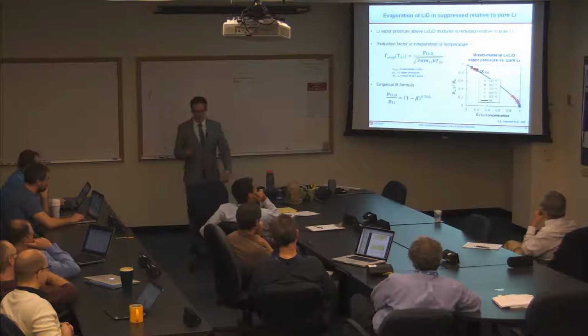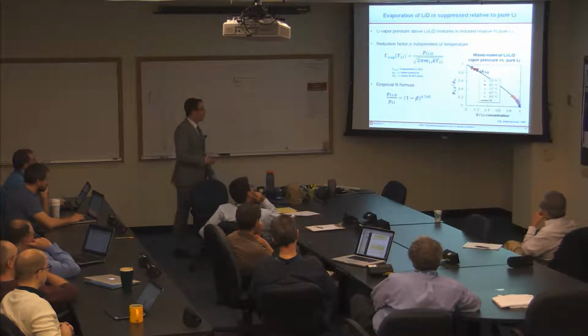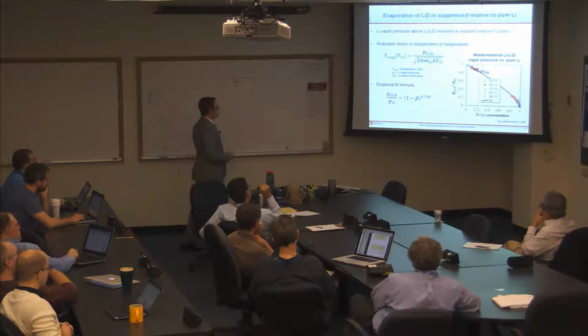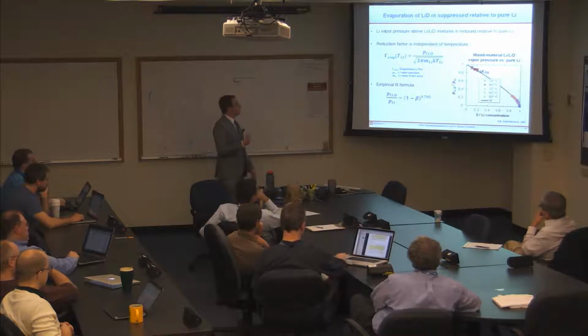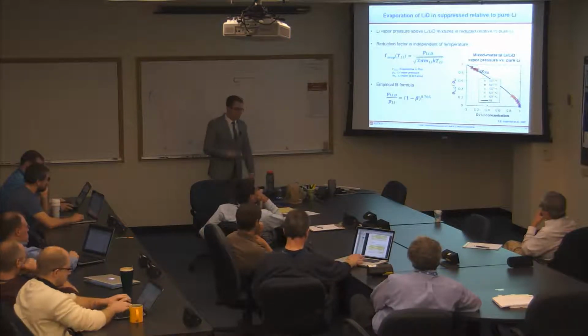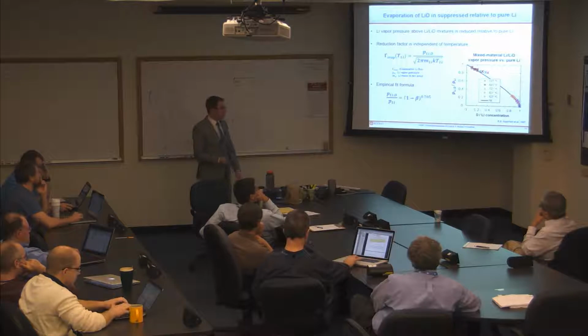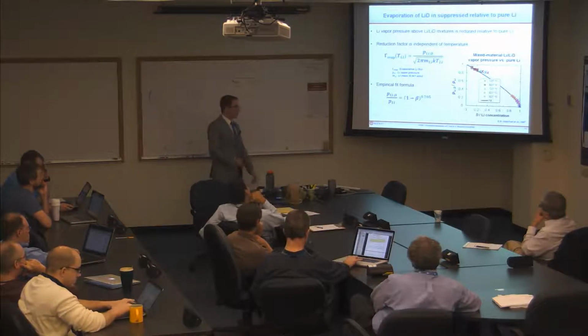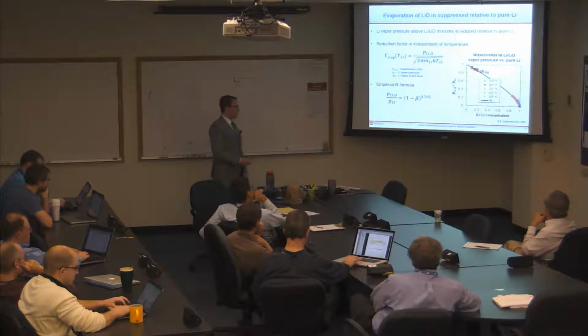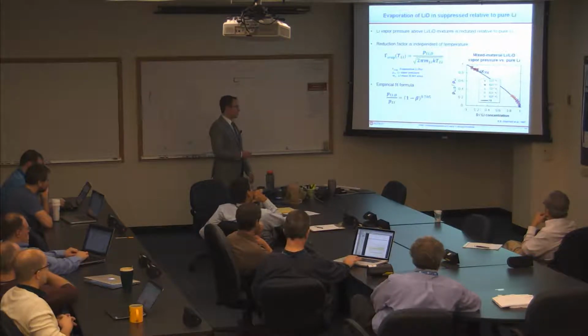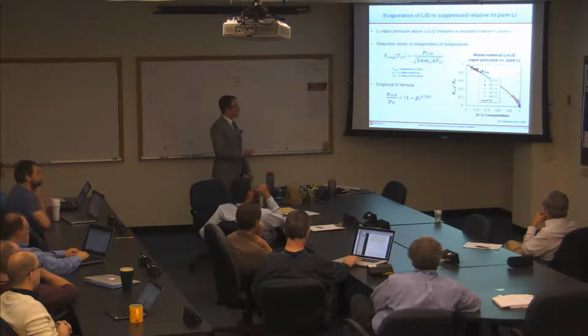Okay, so we've talked a lot about sputtering. So what about evaporation? The lithium vapor pressure above a mixed material lithium deuteride layer is reduced relative to pure lithium. This was not work I did. This is all existing data from a compilation of a number of chemistry experiments.